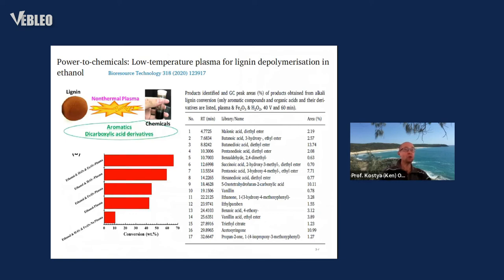If we put, for example, lignin, a common product of biomass decomposition, into water or some solvent, we can run the power-to-chemicals process, using plasma activation of this solution to generate a number of useful chemicals. This processing varies depending on which solvents we use, and also if we use any additional catalytic particles that interact with the plasma discharges that we generate, either in contact with the liquid or inside the liquids.